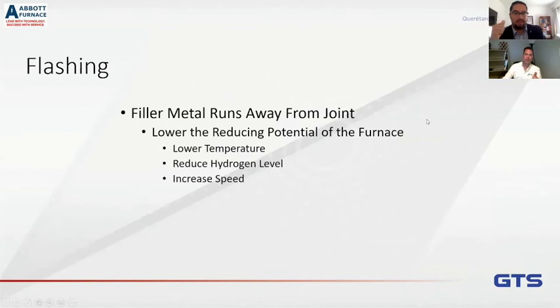Yes, flashing. When you look at a brazed part and you see that the filler metal has just run everywhere, I've had some people say, but it makes the prettiest gold parts. And maybe it does. But what has happened is the atmosphere is so reducing that it's cleaning the surface so much that the filler metal just runs everywhere. And this can cause a reject, because your customer will tell you, I don't want that.